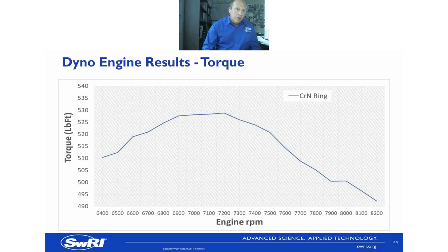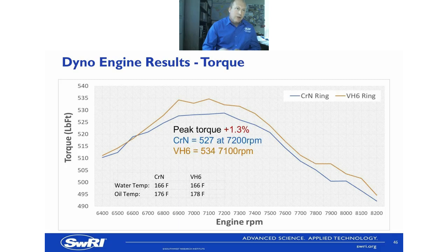So this is the torque that we get from the chrome ring, the original ring that's in the engine. So we do the dyno runs and we measure the torque. And then this is what we got with the VH6 ring. So you can see quite a distinct improvement there. We have a 1.3% increase in peak torque between the chrome ring and the VH6 ring there. A slight change in speed, but not much, from 7,200 down to 7,100, but that's good. And oil temperature and water temperatures registered there, because obviously that's important, because we'd want to know that this is due to the ring and not due to a change in viscosity of the lubricant because of a change in temperature.